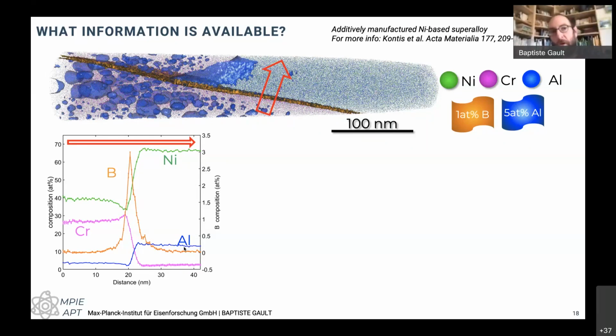And there's been quite a lot of work done. If you look in the literature around superalloys, there's quite a lot of work that has been done just on the partitioning behavior of some of these solutes one way or the other, whether they go to gamma or gamma prime under different conditions. And this then can explain some of the misfit that we see. But I think doing atom probe by itself, increasingly, is kind of useless. We need to fit this within a bigger framework of different techniques that are going to provide complementary information.